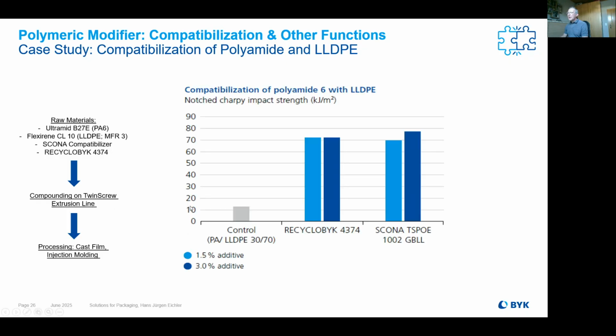And what we saw as a mechanical properties improvement, you see here on that slide. It was a mixture of polyamide and LLDPE with 30 and 70. We take this figure because that's very close to a packaging, which is, of course, a multi-layer structure with 70% LLDPE, maybe on the outer side, and the polyamide is quite often used as a barrier improver, and that's a classical 30-70 mixture. What you see is if you have no modifier, you start up with 12 to 15, something like that. And if you use now RECYCLOBYK 4374 or the SCONA TSPOE, you see with the different amounts of the additives, you really get a nice improvement for the notched Charpy.